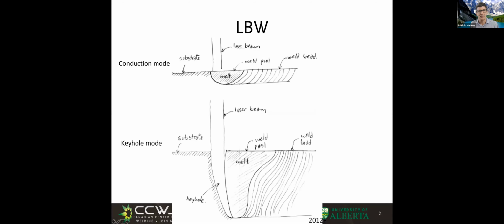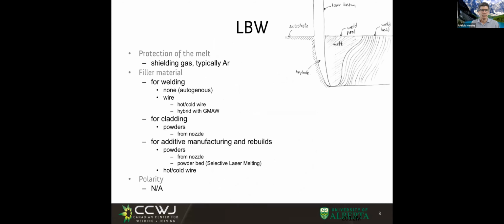This is a schematic that relates to lasers and beams, and we'll see electron beams are very similar. How do we protect the molten metal in lasers? We typically protect it with a shielding gas that is argon. In that aspect, it's not so different than MIG or TIG, right? We are having a shielding gas. Than TIG, because this gas is seldom an active gas. This tends to be typically argon, sometimes argon with some mixtures with helium. But all you want is to prevent the reaction of the molten metal with the oxygen and nitrogen in the atmosphere.